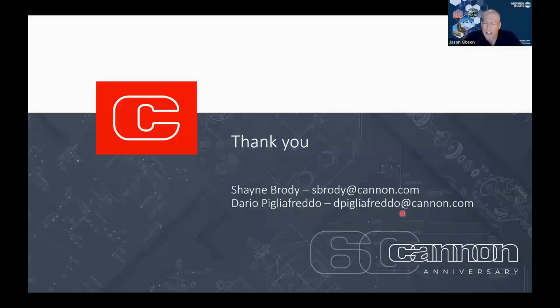Well, thank you, Dario and Shane. I have a few questions for you. I'm really impressed with the overpressure system. You talk about how you get lower void content with it, obviously better aesthetic properties because of the shrinkage aspect. Would you say you are approaching the same type of physical properties you get with a pre-preg material in an autoclave that's processed under pressure? Or is it still shy of what you can get with a pre-preg in an autoclave?